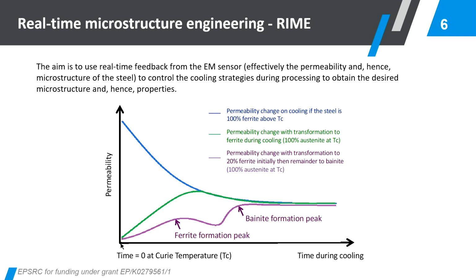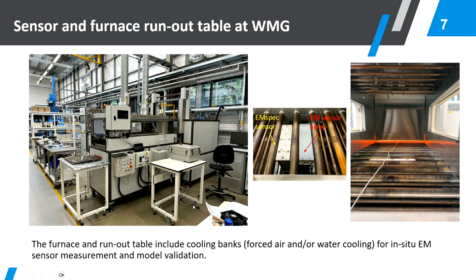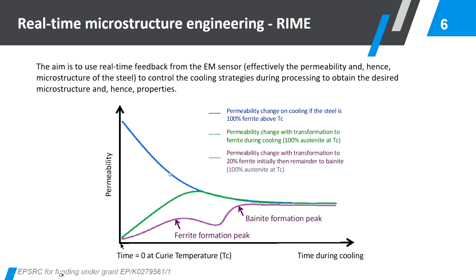It should be ferromagnetic. It's just waiting for the temperature to go below the Curie point. And as the sample gets cooled, you then see a decrease in the signal, simply because the permeability is decreasing with temperature. So that's what you get with a fully transformed microstructure state.